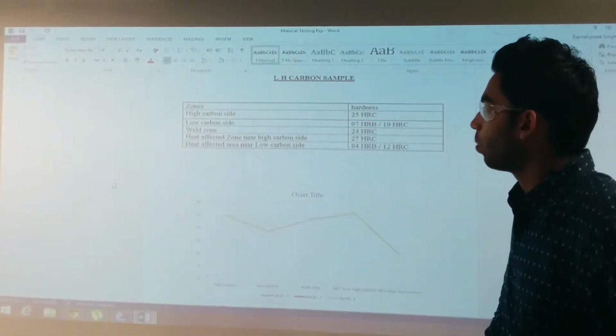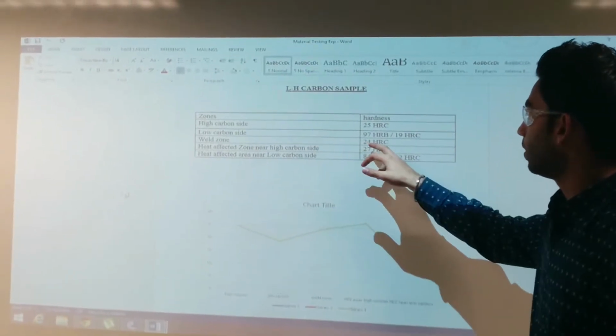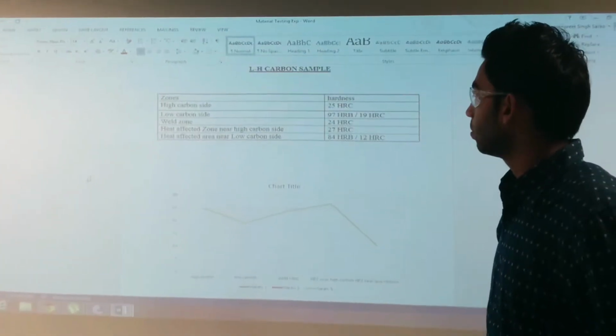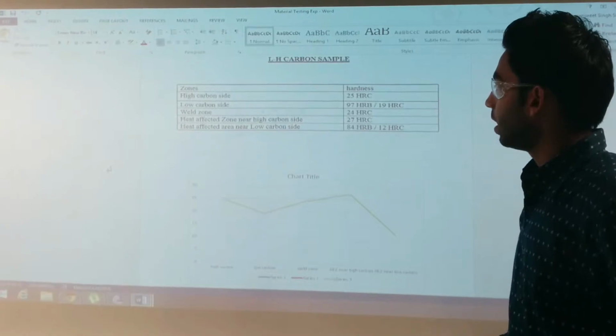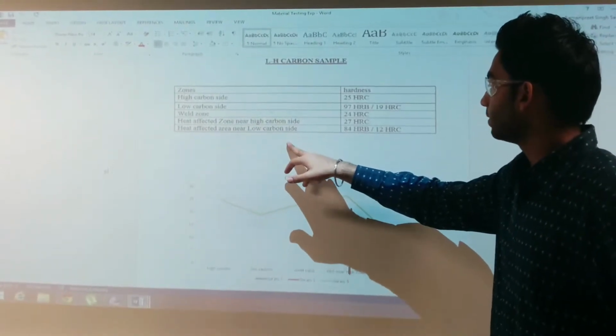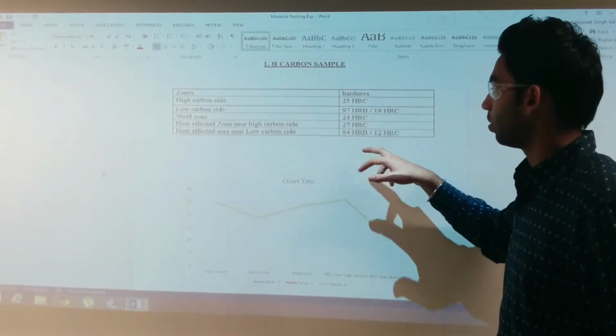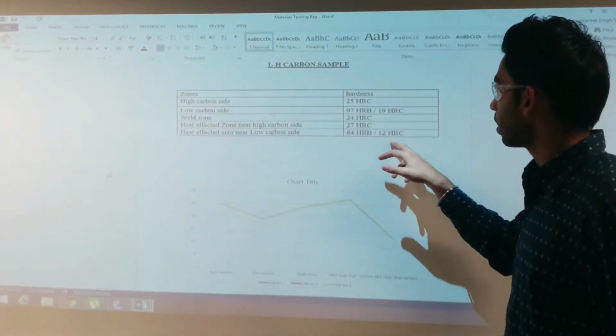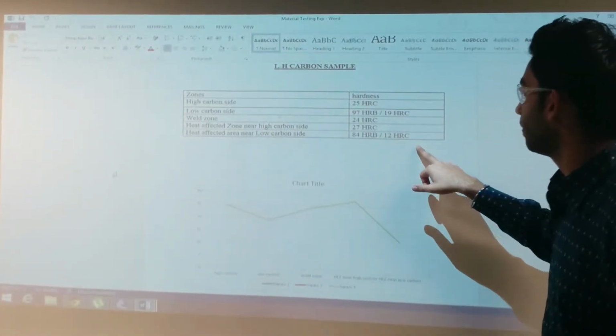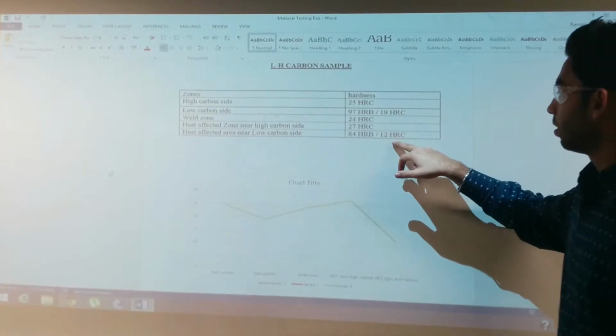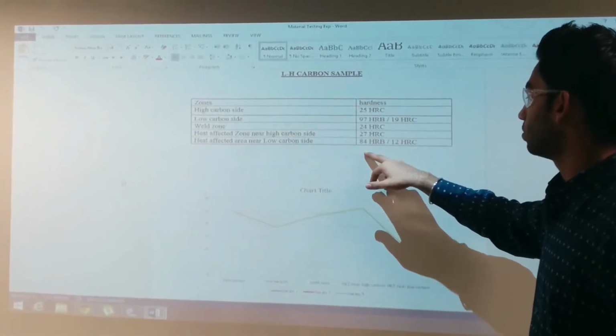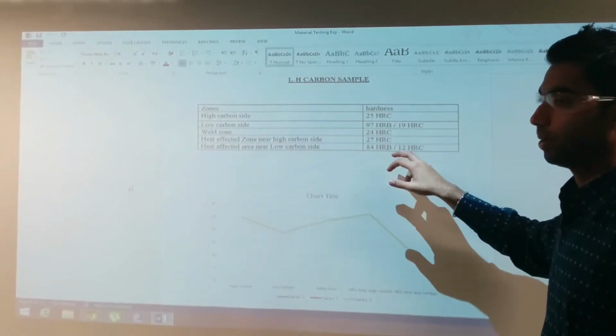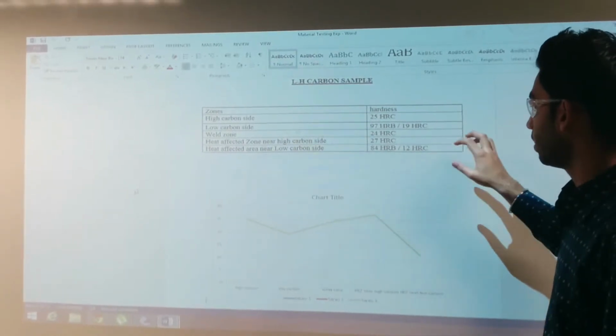Now we are coming to the welding zone. The welding zone was 24 HRC. The heat affected zone was 27 HRC, and the heat affected zone on the low carbon side was 84 HRB, because it was also a soft material, so it can't be measured on the HRC scale. So this is the wrong reading here. It only goes on the 84 HRB scale. The B scale is a bit softer. Again, telling you the thing.